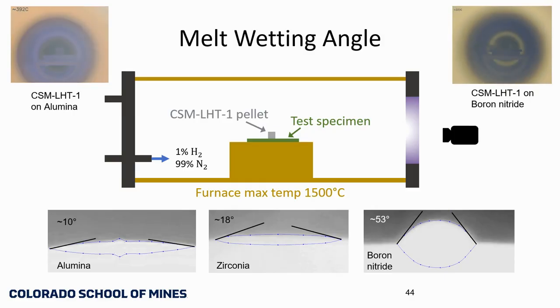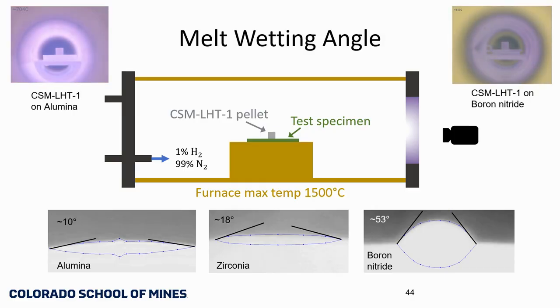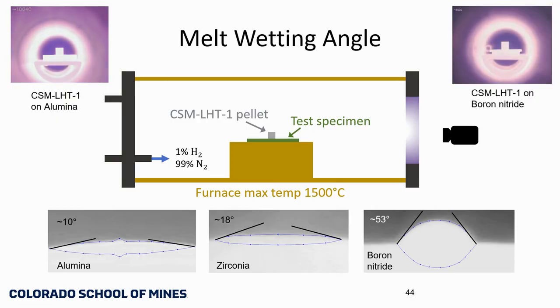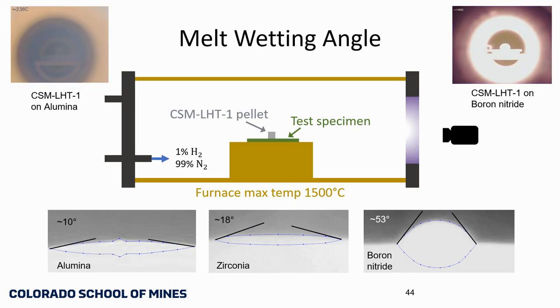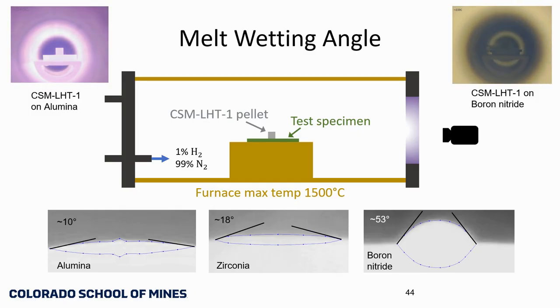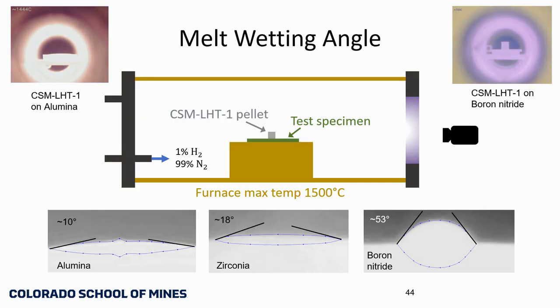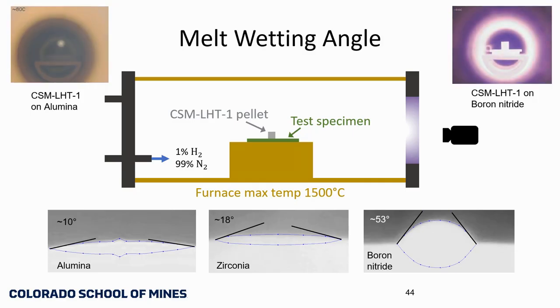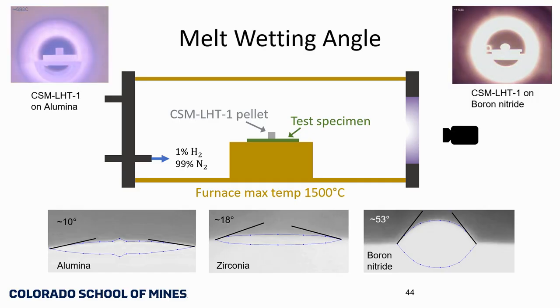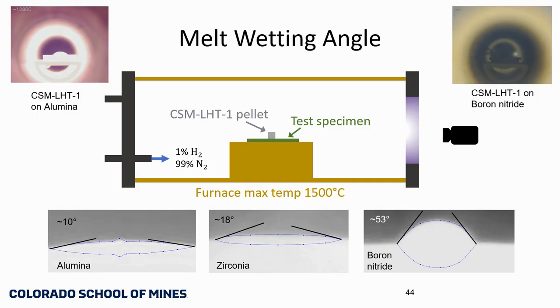This is a wetting angle measurement, and I think the two videos that are running on the upper left and right are interesting. On alumina, the molten regolith wets very easily. We have a little pressed cube of CSM LHT1 in the upper left. It flattens out and wets the entire surface of alumina. On the right, on boron nitride, it sits as a sphere like you would expect with a high surface tension material.